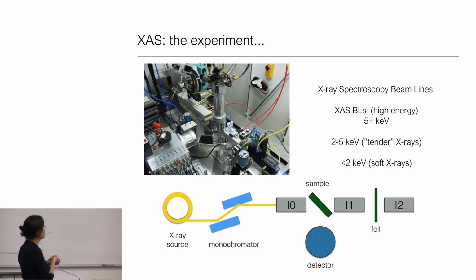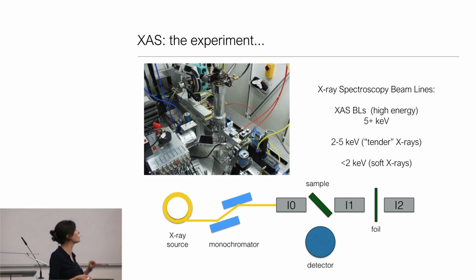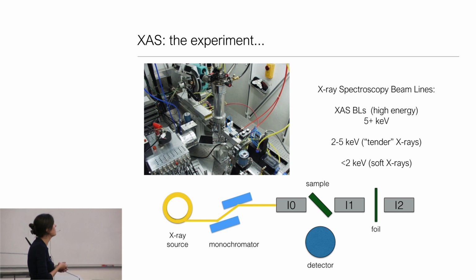Now, the advantage we have with hard X-rays, and by that I mean greater than 5 keV or greater than 5,000 electron volts, is the X-rays themselves have a relatively long path length in air. And this means that I can always simultaneously measure a reference foil, which is quite helpful in terms of thermal drift or any instabilities. We typically know our reference energy quite well because we're measuring it simultaneously. What you'll see, though, is that my sample here is rotated by 45 degrees, and I have another detector here. And this is in part because the phrase X-ray absorption spectroscopy is a little bit of a misnomer.